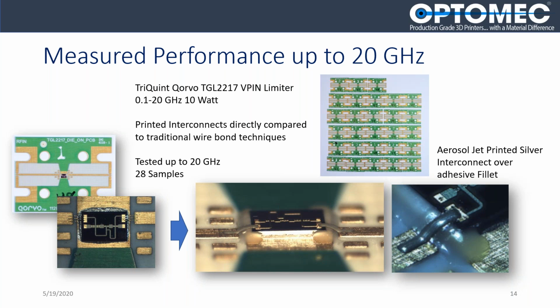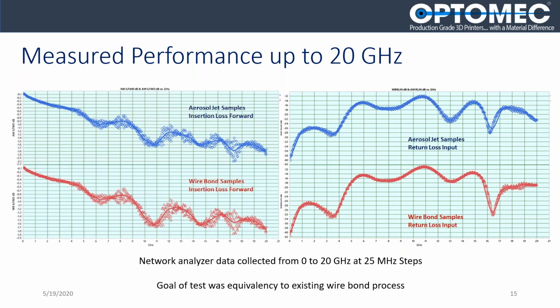Now, I want to note that we did not optimize the impedance matching capability that I mentioned earlier. This interconnect is straight. And the purpose of this test was equivalency, right? We're trying to match the wire bond capability. And I think what we were able to show by collecting the network analyzer data here, and this data was collected in conjunction with the American Competitive Institute, or ACI, and again, the goal was just to match equivalence. And this test was very, very successful, demonstrating that both insertion and return loss performance of these interconnects directly matches the traditional wire bond configuration.